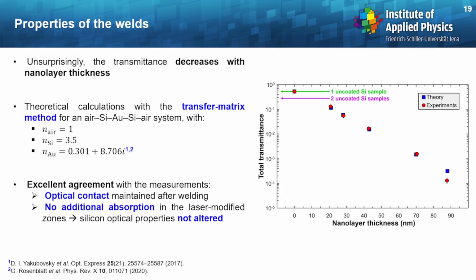Concerning now the properties of the welds, here is displayed the total transmittance experimentally in red as a function of the nanolayer thickness. And what one can see here is that, unsurprisingly, the transmittance of course decreases with the nanolayer thickness. And to explain this, we turn to theoretical calculations with the transfer matrix method, with the following refractive indices, and we got basically an excellent agreement, as you can see here, between the simulations and the experiments.